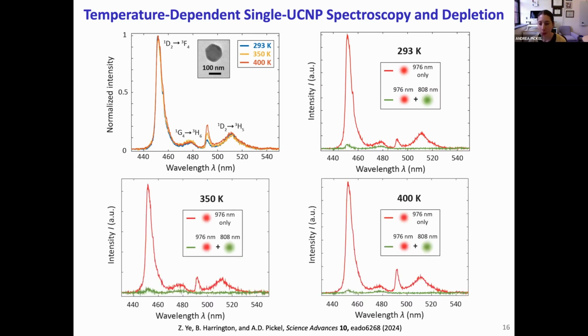At higher temperatures, we maintain the same depletion performance. And across all temperatures, we can deplete both our temperature-dependent peak and the longer wavelength peak near 515 nanometers very well. And even though the temperature dependence comes from one peak, we're still interested in a ratiometric approach, since that has advantages over working with absolute intensities. And so going forward, we'll focus on these two peaks.